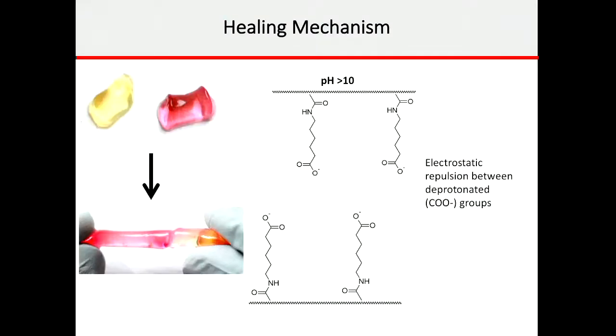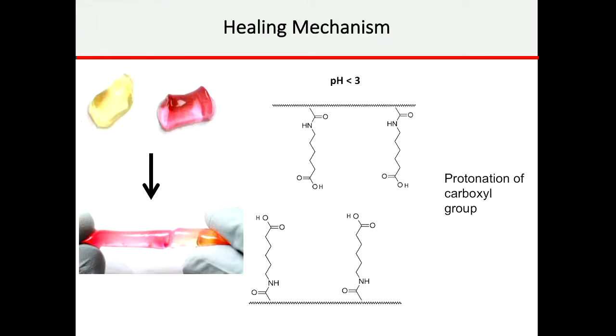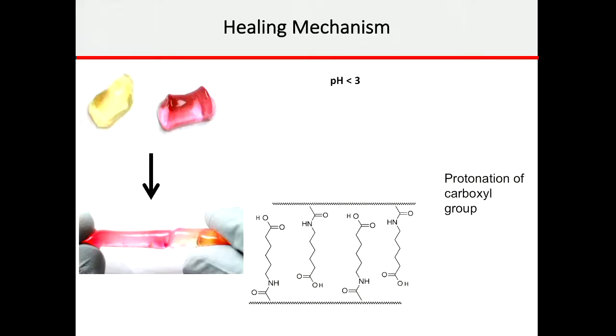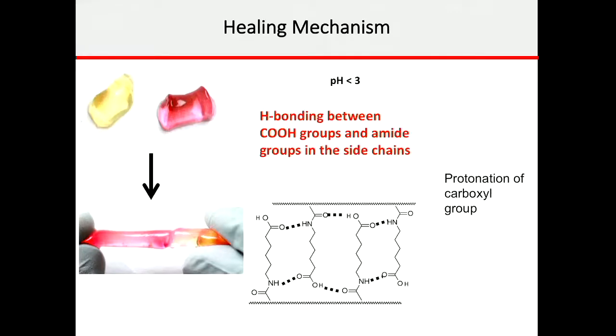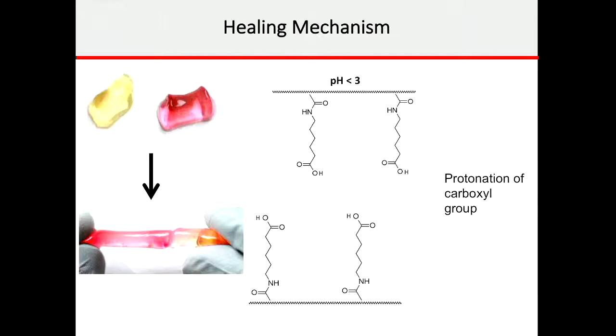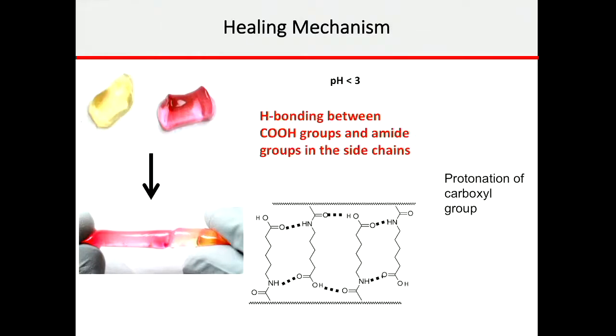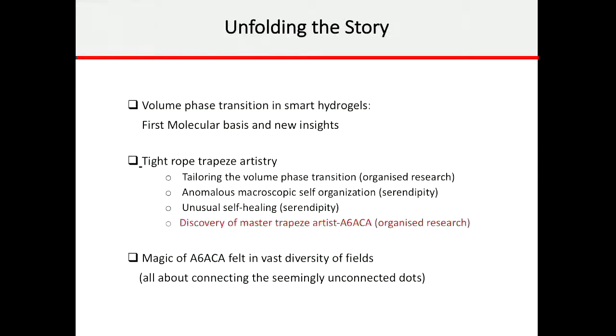the healing mechanism is like this, that when you have a large pH, for example, there is an electrostatic repulsion between the deprotonated carboxyl groups. Then you lower the pH, there is a protonation of these, and then you see the interweaving of the two chains at the interface, and then the hydrogen bonding between them, and that is how the healing actually takes place. Okay? Or in other words, if you go back to pH 10, whatever has healed will disappear, and if you lower the pH, the complete healing will take place. So it's a reversible process that you see. And it's extremely rapid, so as to say.